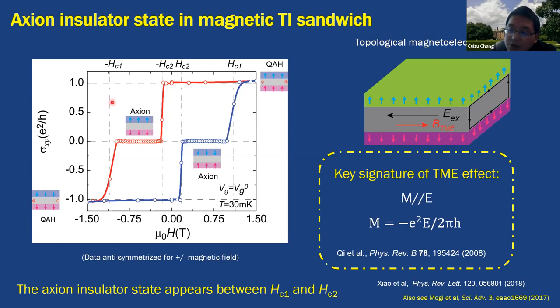This axion insulator state is a good candidate for the detection of the topological magneto-electric effect. And what is the topological magneto-electric effect? It is different from the conventional magneto-electric effect. Here the electrical polarization is parallel with the magnetization in the bulk, and the coefficient between the magnetization and the electrical polarization is quantized. This work is still ongoing in my lab.